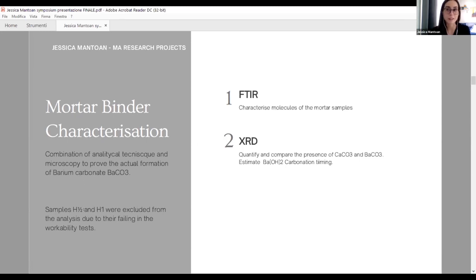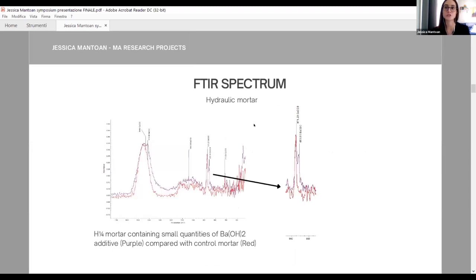So they completely failed the test, and considering that if a mortar is not workable, it cannot be used, for this reason I decided to exclude those two groups of mortar from all my research. Coming back to mortar binder characterization, I decided to characterize the binder of all my mortars. I decided to use FTIR and XRD. And now I'll show you the results.